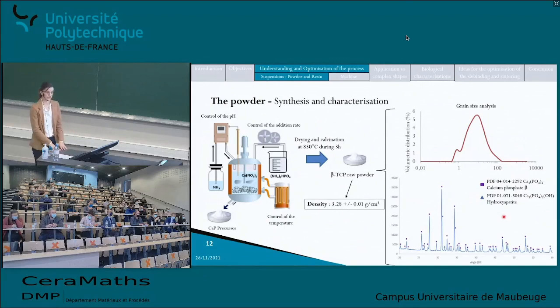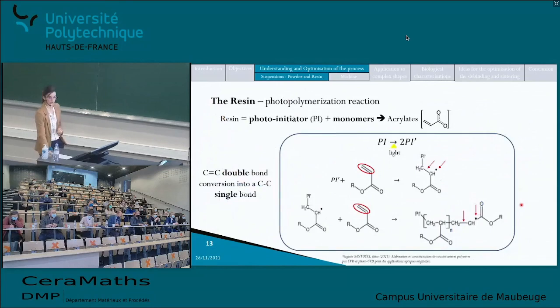So the next step was the study of the resin. The resin is, as I mentioned, at the center of the stereolithography process because of the photopolymerization reaction. The resin is composed of a photoinitiator and a monomer. In the literature, most of the monomers used in the SLA process are acrylates. Basically, the photoinitiator interacts with the light and gives two radical photoinitiators that are then able to react with the acrylate monomer, breaking the carbon-carbon double bond into a single bond and enabling the monomer itself to react with another monomer, therefore giving the 3D photopolymer network.